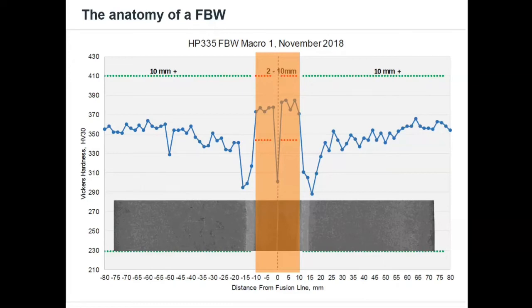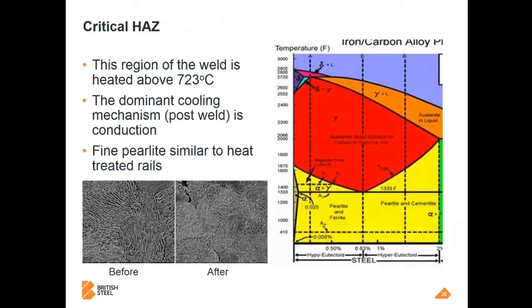Finer pearlite. So going back to the iron carbon phase diagram, you can see that we heat up during welding into the austenite region. We re-austenitize the steel. The carbon goes back into solution. We then weld them together, forge weld them together, maybe 150 ton forging pressure. We then allow it to cool and it retransforms, but at a faster rate than previously, so we end up with a finer pearlite.